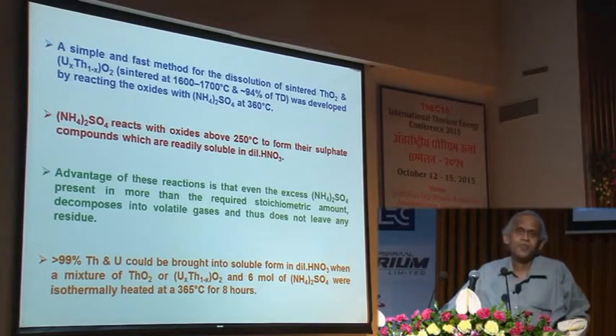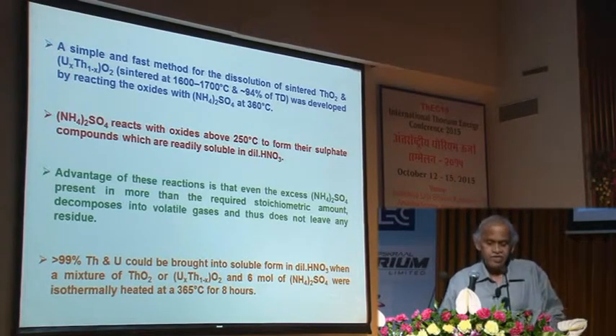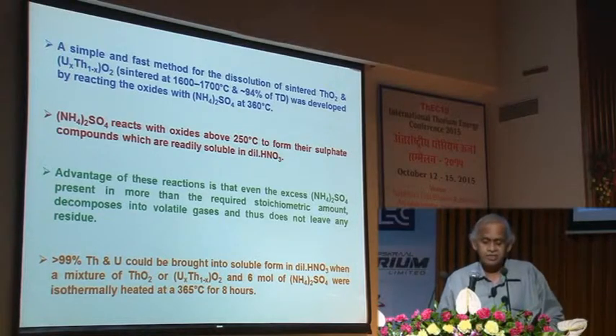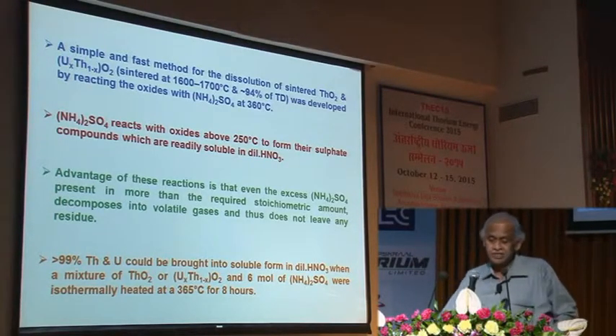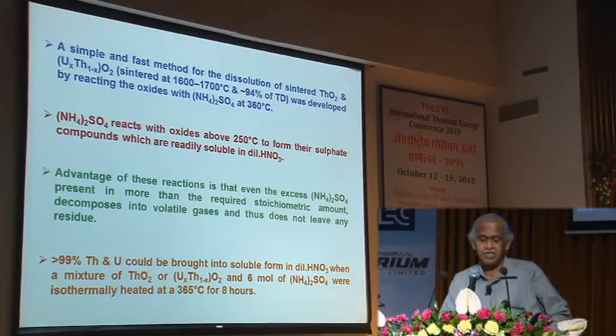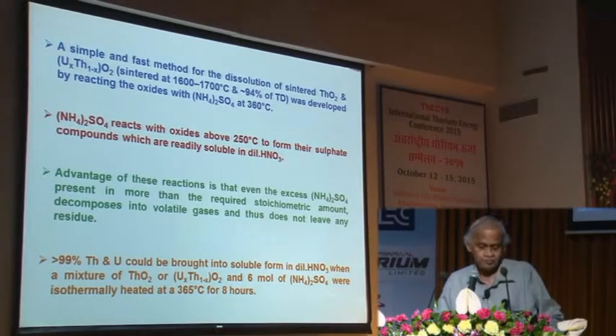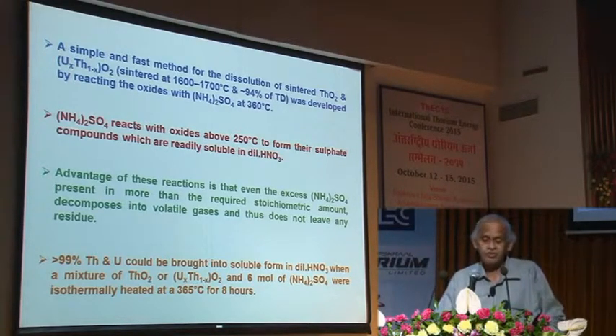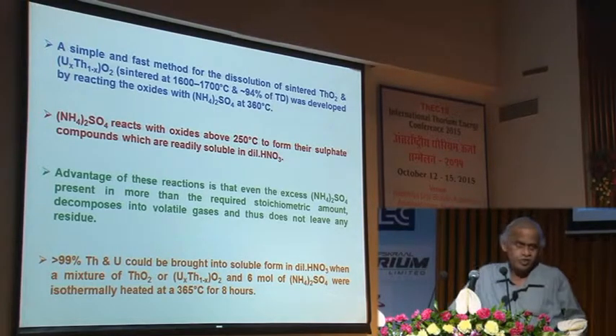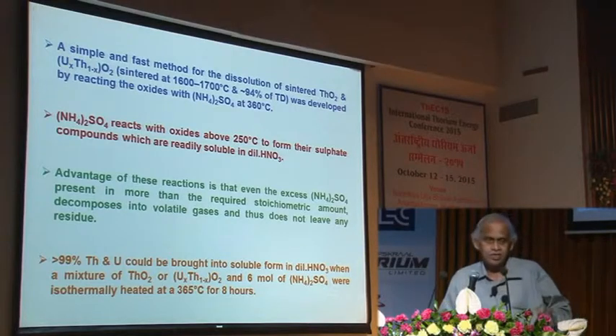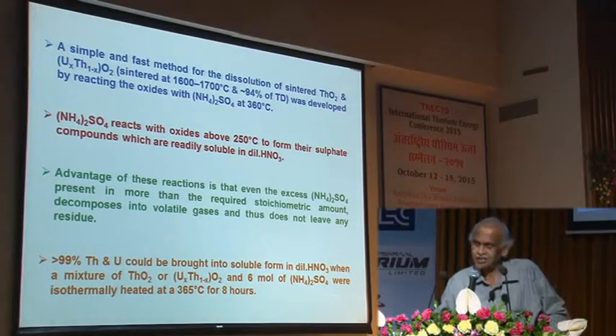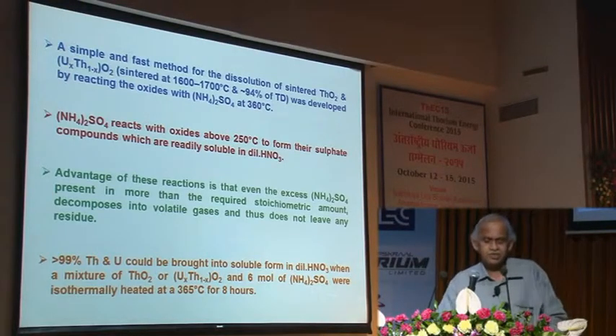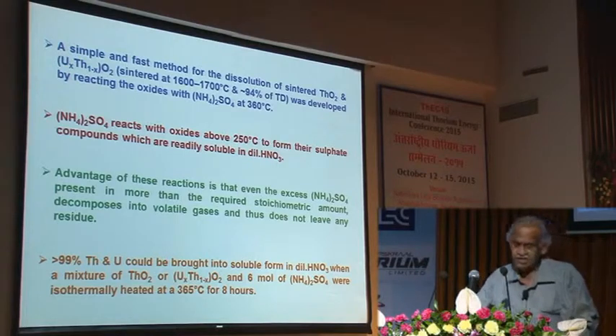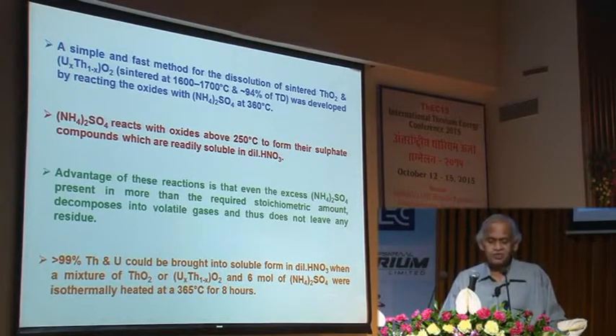But we have completely used a different technology, a simple and fast method for the dissolution of sintered thorium oxide and uranium thorium oxide, sintered between 1600 to 1700 degrees Celsius, which has got 94% theoretical density, by using a solid solution route, by reacting oxides with ammonium sulfate at 360 degrees Celsius. It is a solid reaction. It does not go in for nitric acid, hydrogen fluoride. The chemistry is only that it reacts with oxides at about 250 degrees Celsius, ammonium sulfate, to form their respective sulfate compounds, which are readily soluble in dilute nitric acid.